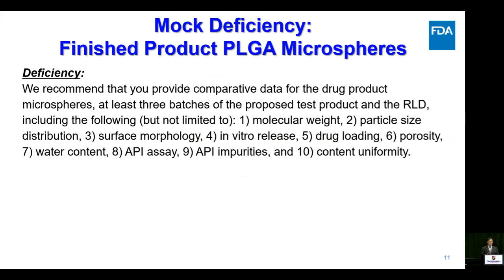Now we move to the qualitative sameness for the finished product. Here is an example of a deficiency. We recommend that you provide comparative data for the drug product microspheres, at least 3 batches of the proposed test product and RLD, including the following tests: molecular weight, particle size distribution, surface morphology, in vitro release, drug loading, porosity, water content, assay, impurities, and content uniformity.